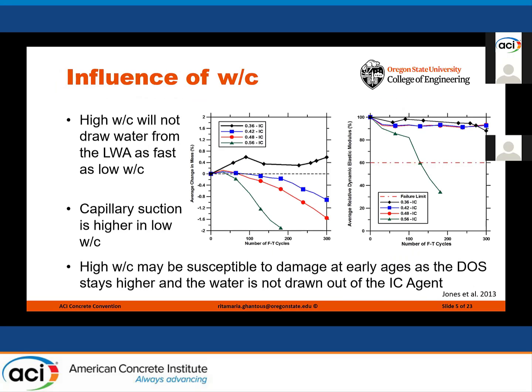Also, in the study of Jones et al., we can see based on weight measurements, the middle graph in this slide, and the dynamic modulus of elasticity measurements, the right graph, that internally cured mixtures with a low water to cement ratio perform better than internally cured mixtures with a high water to cement ratio. So in these graphs, the higher the line, the better the freeze-thaw performance. So we can see that the black line, which corresponds to the low water to cement ratio, has a better performance for freezing and thawing damage.